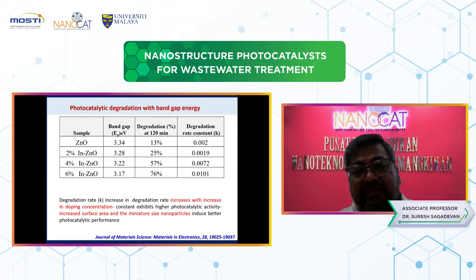You can see from the table, which confirms the high degradation rate constant for only the 6% indium zinc oxide, which is 76%, which means that the high degradation rate constant is confirmed with high doping. When you add more doping, the dye degradation percentage increases, which is confirmed from this analysis. So therefore, we conclude that this material has potential. We are not using visible light, but even though we are using UV light, you can see that the maximum degradation is 76% in the time. This is a potential material for wastewater treatment applications.